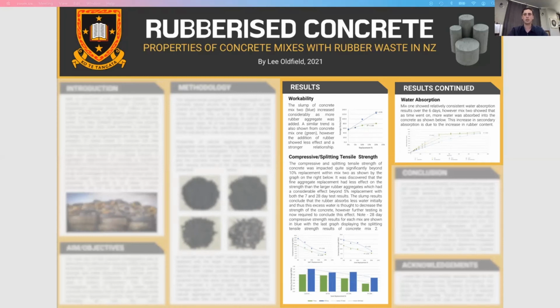The last graph on the left displays the splitting tensile strength results for mix 2, and it can be seen that the addition of rubber up to 10% has minimal effect on the splitting tensile strength of concrete, which is a desired result. The water absorption results for both mixes show a slow initial water absorption. However, beyond 6 hours and through the secondary stage until 6 days, the water absorption increases with the addition of waste rubber.